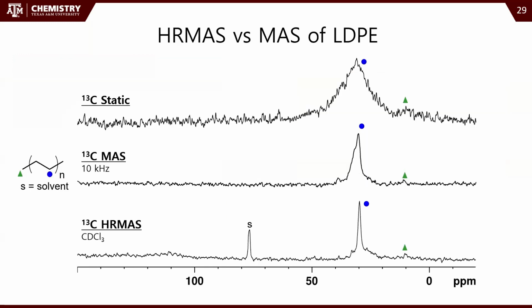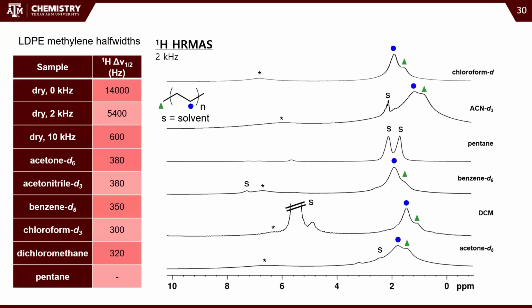So if we have no magic angle spinning, we get really broad signals. If we have 10 kilohertz, we get sharper signals. And then if we have HR MAS, which is soaking with, in this example, chloroform, and then 2 kilohertz of rotational speed, then we get even better resolution. So HR MAS is a nice technique if you want to improve the resolution of the polymers. And we applied that, like Dr. Blumel said, with other companies characterizing their polymers and seeing if we can make chemical changes and see that.